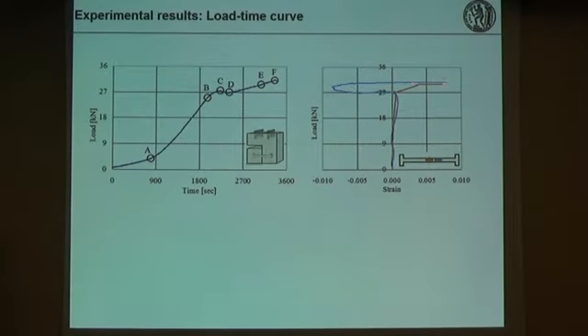the orange line is the result of the strain gauge placed at the interface between the two marble blocks, while the blue line is the result of the strain gauge placed on the movable marble. So it's observed that at a load approximately higher than 27 kilonewtons, there is a big deformation occurring on the connector.